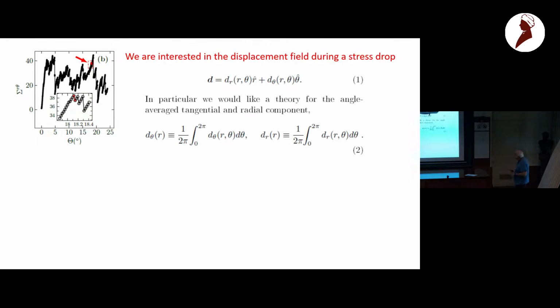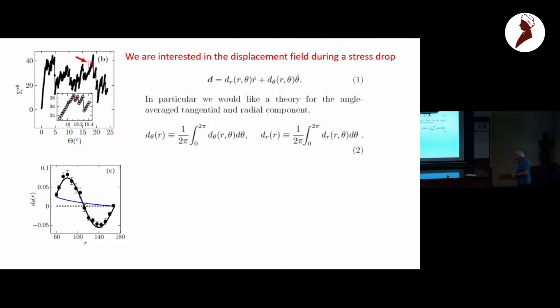Okay, and when you have a displacement field, you can break it into 2 components, the radial component and the angular component. Both of them are functions of both the radius and the angle. And in particular, I would like a theory for the angle-averaged tangential and radial components. So this is the angle averaging. You take the quantity averaged over the angles, and you get a function of the radius alone. So both the angular component as a function of r and the radial component as a function of r. And I want to have a theory for those in order to understand what is going on. So what is the challenge? The challenge is, here is an example of the angular part of the displacement field as a function of r. This blue line, embarrassingly, is the prediction of elasticity theory.